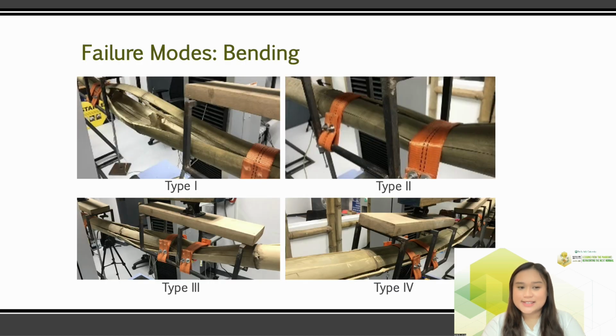For our results and discussion, multiple failure patterns existed for each testing made onto Bambusa blumeana. The bending failure modes were categorized in 4 types. Type 1 is the ideal failure, existing in the middle, right into the constant moment zone. Type 2 is where the failure mode occurs in the point of load application. Type 3 failure mode happens in the constant moment zone, where loading was applied extending to the middle. And type 4 is a total collapse of the bamboo column.